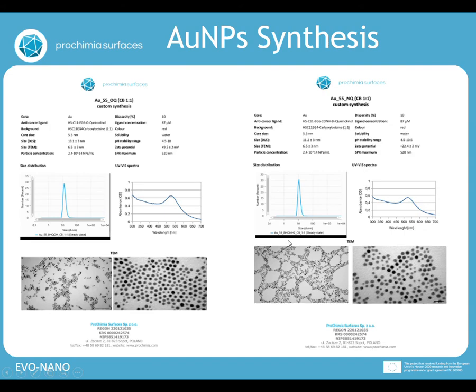So we obtained gold nanoparticles of 5.5 nanometers with the carboxybetaine background and the quinolinol connected through the oxygen in the ratio 1:1, and the UV-vis spectrum simply reflects the plasmon resonance of the metallic core, which is around 520 nanometers, and the DLS measurements showed the size of the nanoparticles about 13 nanometers.